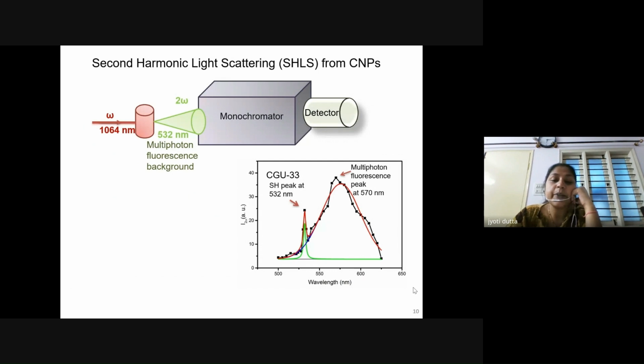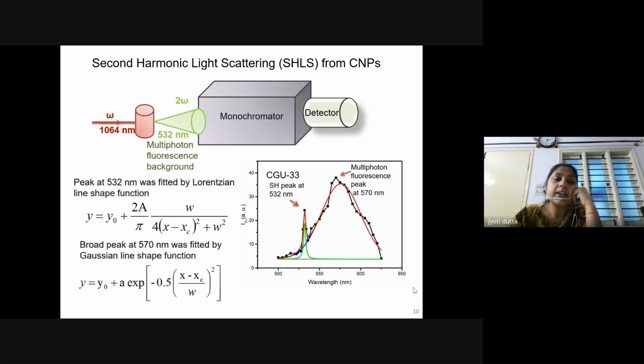This is a multiple peak fitting. And these are the two peaks, two line shape functions which we have used for this spectral fitting. Now, why we have opted for a Lorentzian line shape function for the peak at 532 nanometer and a Gaussian line shape function for the peak at 570 nanometer is because the scattering is an instantaneous process. So we expect that there should not be any broadening which is taking place for this second harmonic peak. And that is why we have opted for a Lorentzian line shape function.